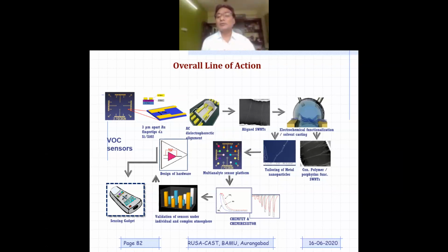As far as the electrochemical part, we are still using electrochemical polymerization, but this is going to be charge-controlled potentiostatic deposition, because you can terminate your potentiostatic reaction on the basis of charge. Many electrochemical workstations exist, but in the CH electrochemical workstation you have this facility. You set the charge, and once the charge is reached, the reaction is automatically terminated. We tested from 3 microcoulomb up to 100 microcoulomb and got different results, but unfortunately I'm not going to show all the results because time will not allow. But I'm showing you how the devices can be developed.